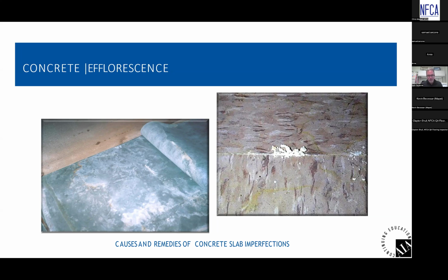It's interesting when you pull up tile, when there's an efflorescence problem, you pull up the tile and you can see the trace of salts all the way around the outside of the tile, where I guess the moisture vapor can escape through the space, the joint. Yeah, that's the path of least resistance. Absolutely. So at that point where it's escaping, it's depositing the salt on the surface and leaving that mark around the outside of the tile. Yep, absolutely.